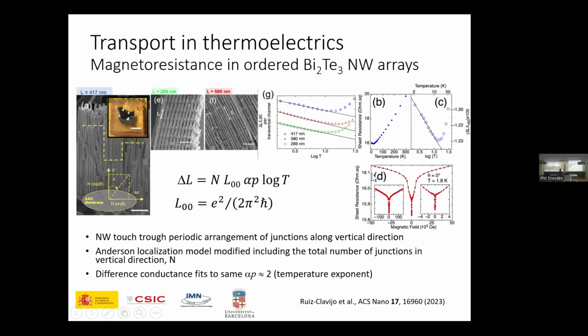Next example, here we have a very good thermoelectric, the material that is currently used in all Peltier coolers and things like that, so bismuth telluride. In this case, the question was to study not the material itself, but how the nanostructure that was created by the colleagues affects the transport, or how electrons move along this particular structure in an otherwise very well-known material. Yeah? And here the structure is an array of nanowires that go vertically, like in the vertical of the image, but with the characteristic that they have nodules that connect the wires horizontally. Yeah? So in that case, you can measure that array as a whole, as if it were a film.